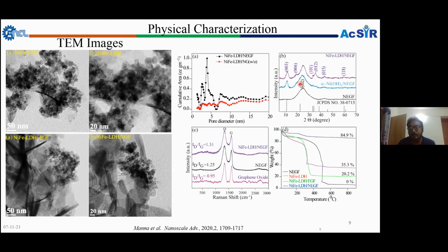To know the crystal phases formed in the nickel iron layer double hydroxide over the 3D nitrogen doped entangled graphene, we checked the nitrogen doped entangled graphene. The graphitic 002 peak comes around 26 degrees. In the presence of nickel hydroxide over the nitrogen doped entangled graphene, a similar 002 graphitic peak is observed, and one extra peak comes from the nickel hydroxide, which we confirmed through the JCPDS value, showing the formation of nickel hydroxide. After incorporating iron into the nickel hydroxide, the 002 peak of the nitrogen doped entangled graphene remains, and other peaks appear, which we compared to the JCPDS number, showing the formation of the nickel iron layer double hydroxide.